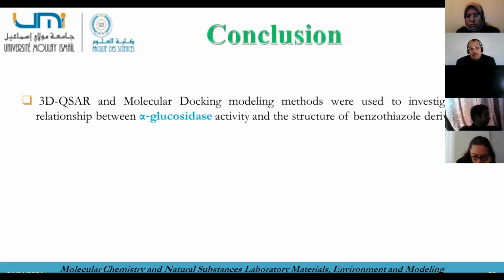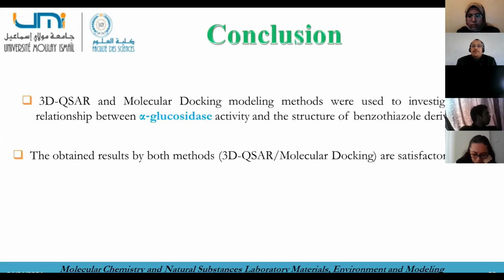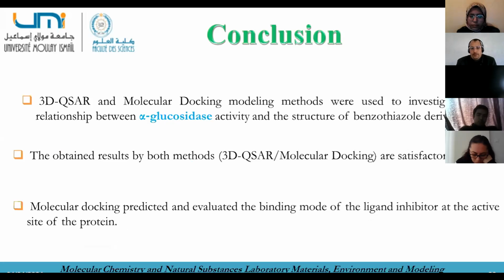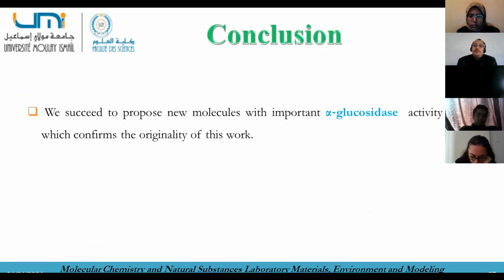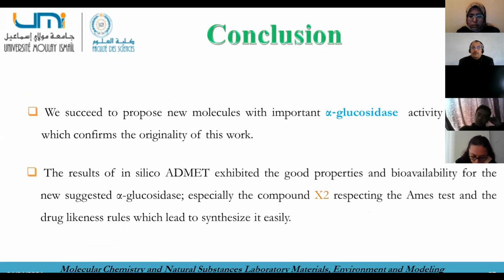Conclusions. In this study, 3D QSAR and molecular docking methods were used to investigate the relationship between alpha-glucosidase activity and the structure of benzothiazole derivatives. The results obtained by the methods are satisfactory. The molecular docking predicted and evaluated the binding mode of the ligand inhibitor at the active site of the protein. We succeeded in proposing new molecules with important alpha-glucosidase activity values, which confirms the originality of this work. Finally, the in silico ADMET results exhibited good bioavailability properties for the newly suggested alpha-glucosidase inhibitors, especially compound X2, respecting the Ames test and the drug-likeness rules, which leads to easy synthesis.